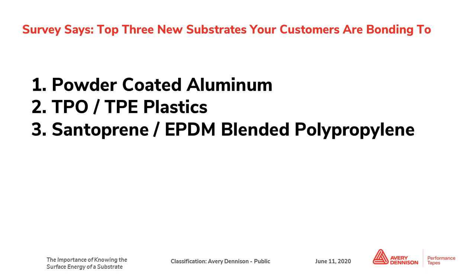And we screened several different tapes to this particular substrate material and found that our FT3043 or the FT1943 PP, which uses our LSE modified acrylic, did a fine job of bonding to it. But some of the other tapes that we typically recommend for low surface energy did not perform as well. So we had to be careful with things like that. And as Deanne mentioned, we'll be adding materials and substrates to the core series. If it's something you don't see on the core series, that's where you would want to ask our customer service, our technical service team, to get you the best recommendation.